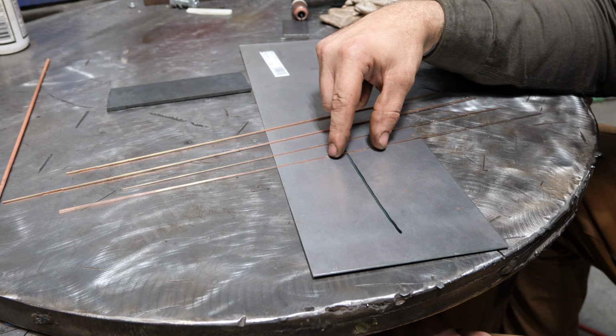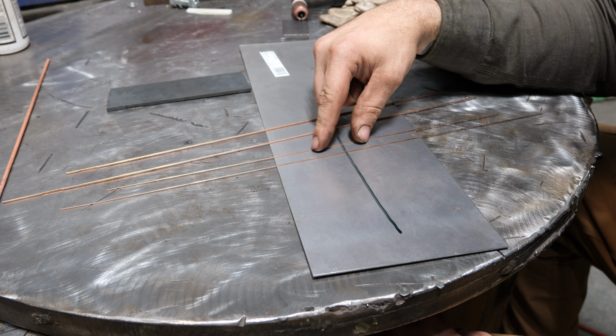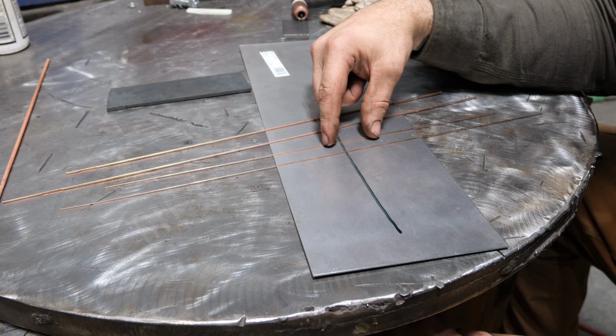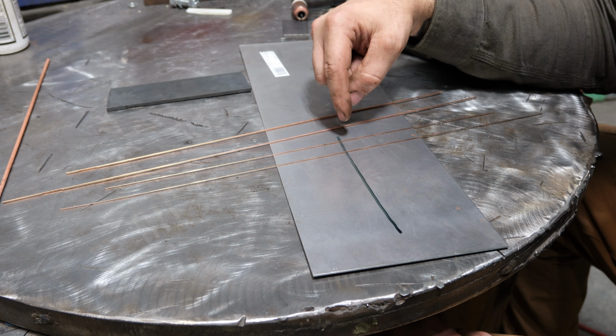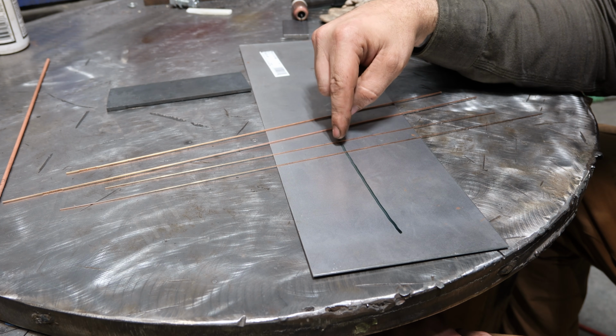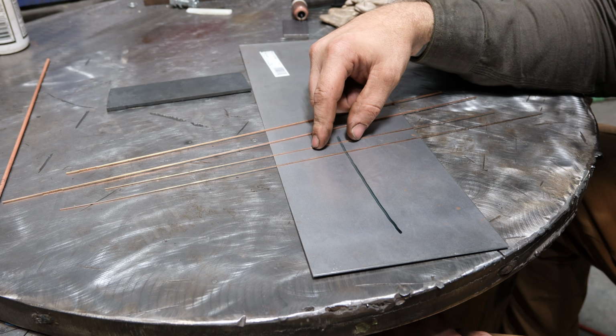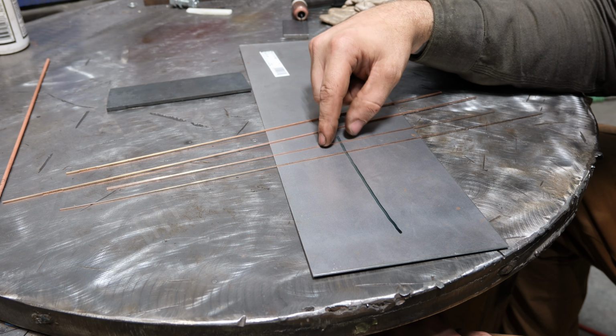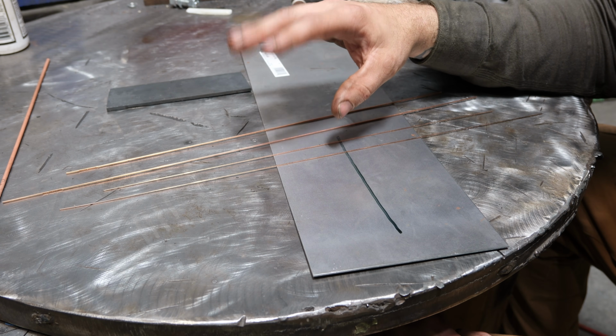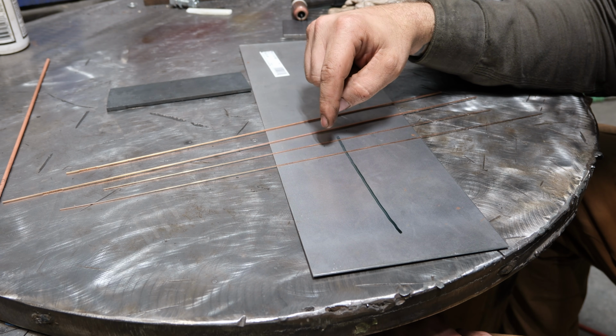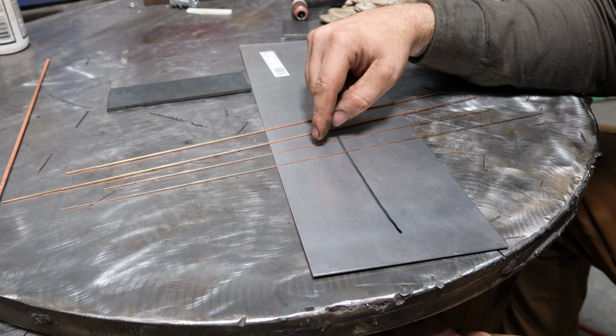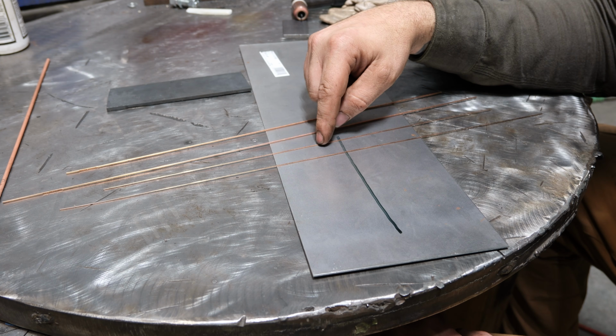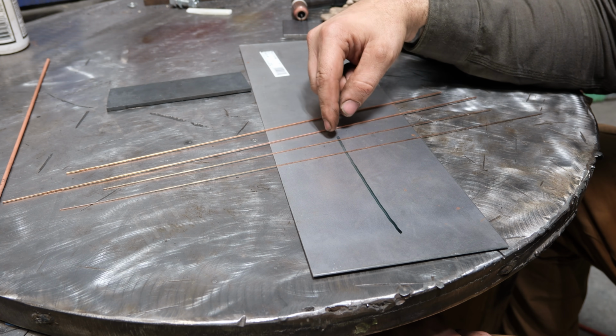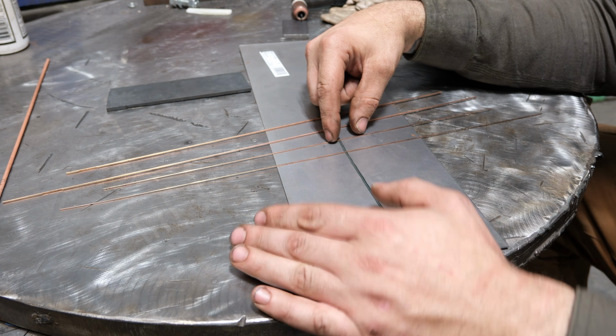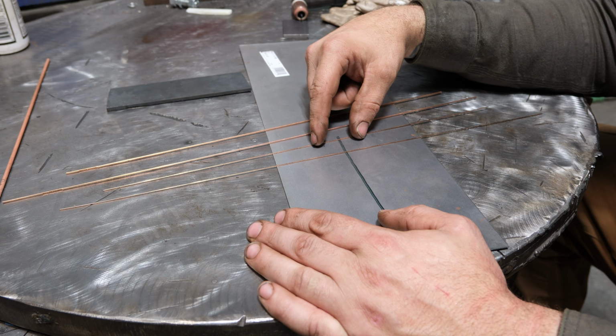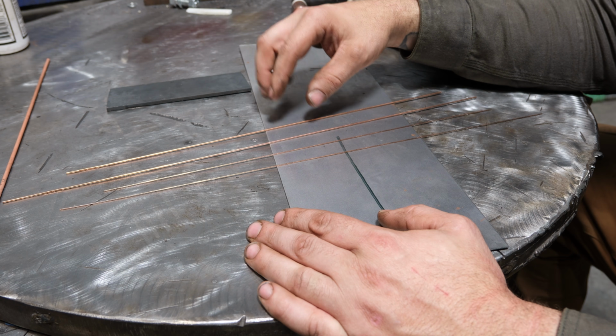Now, there's a lot of other choices that are smaller. Here I have 035 wire, so it's basically the same as MIG wire, just in a straight piece of wire. 035 is tremendously helpful on very thin material, like auto body thickness. I much rather use 035 to weld on say 18 and 20 gauge or thinner. You can deposit smaller welds, it melts off better, it's just far easier. Now the downside is if you use too small of a wire for what you're welding, it's just going to melt off and ball up on the wire, and then it's going to be very difficult to weld with.